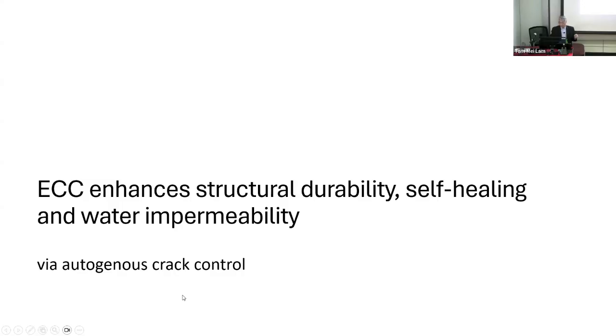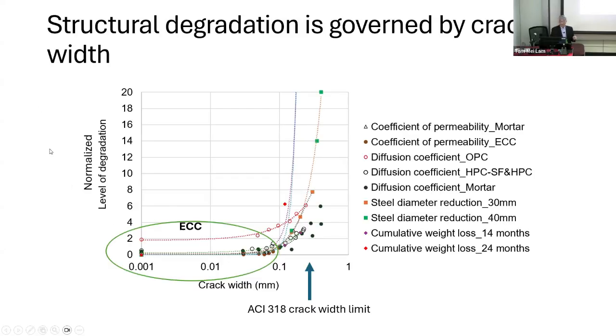Okay, so let me start with durability and self-healing. So this is the chart that I mentioned a moment ago, plotting the level of degradation against crack width. Some of these are our own data, but others are collected from the literature by other research groups. But no matter which kind of degradation we are talking about, water permeability, chloride ion diffusion, corrosion of the steel bar inside the material, and so on, it doesn't really matter. They all show this interesting behavior.